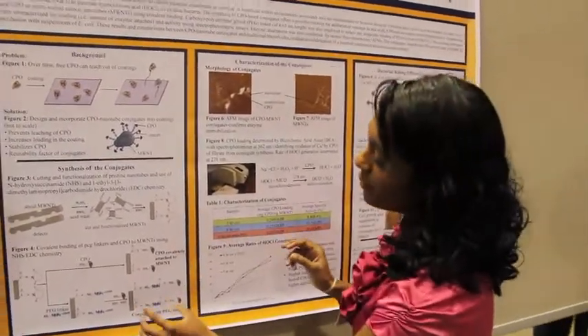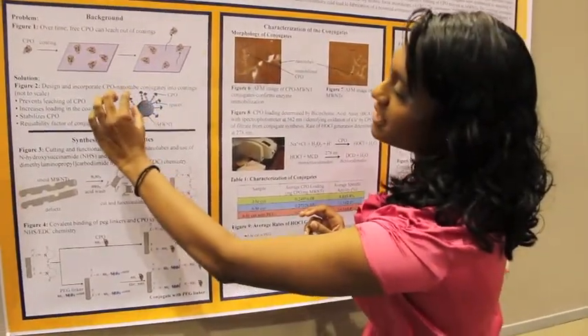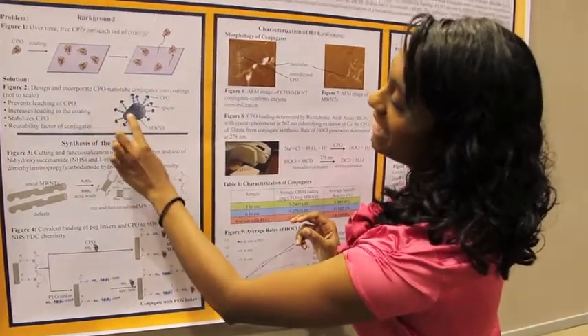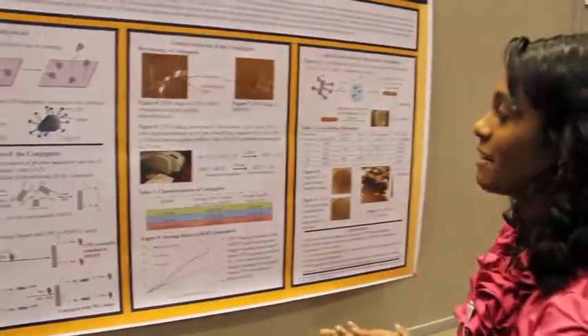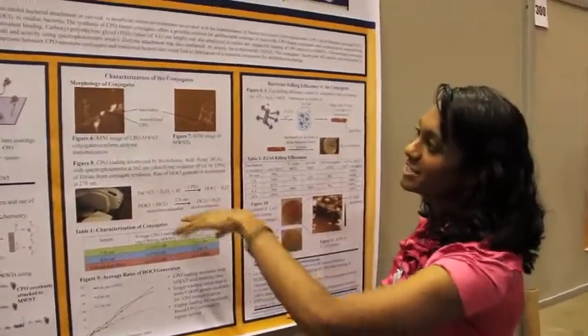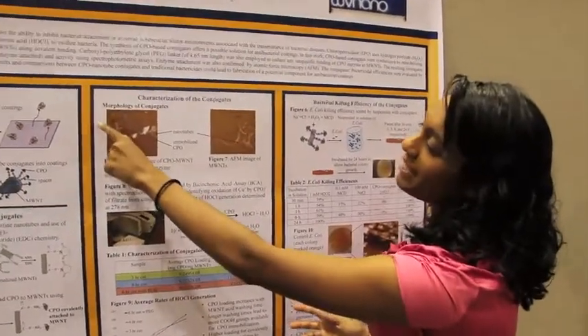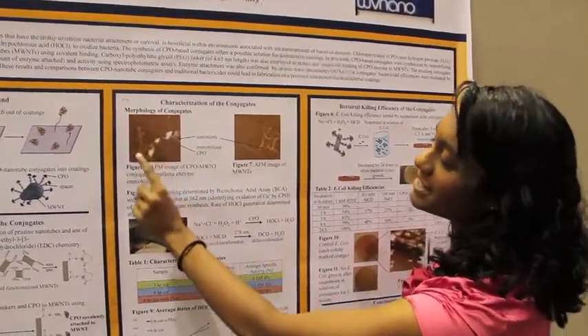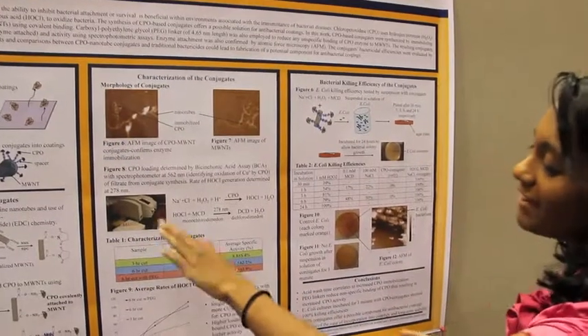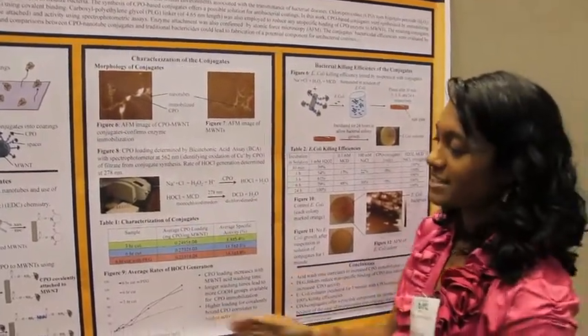Okay. So we basically synthesized these nanotubes. We also saw what would happen if we added spacers between the enzyme and the nanotubes and saw what the effects of that were. So we took some AFM images, basically confirmed that the enzymes were loading onto the nanotubes, and then we found out how much of the enzyme was loading onto the nanotube.